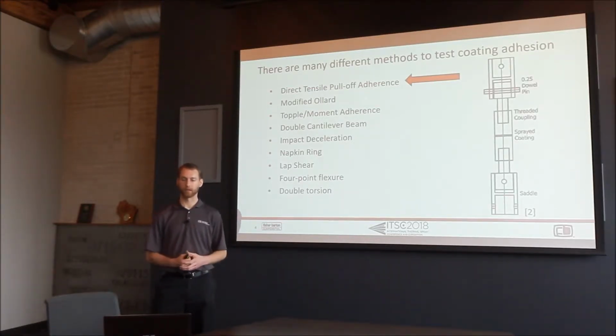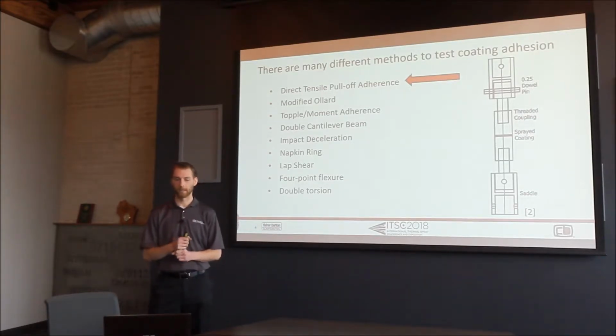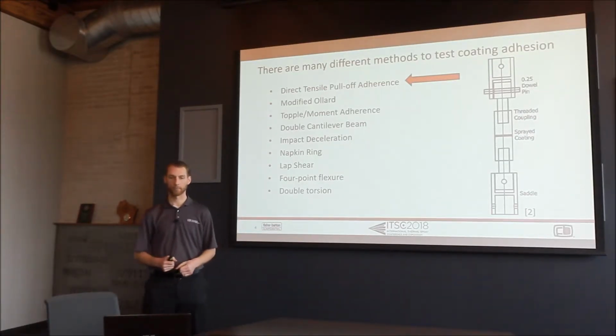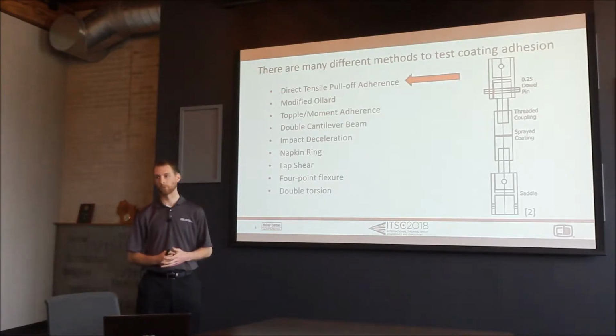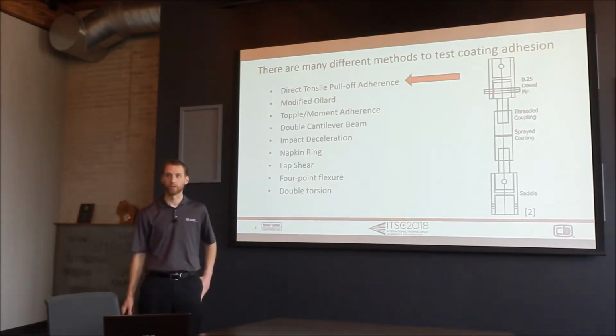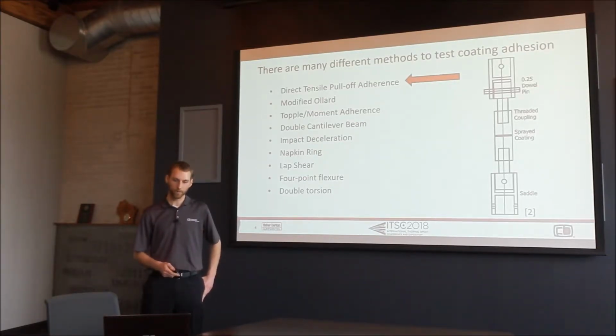Really this test, simply put, you're putting uniaxial tensile stress on the coating after applying an adhesive to the surface and then pulling directly vertical. So that's a force normal to the coating surface. And this is the most common test done in industry for qualifying a thermal spray coating and process.